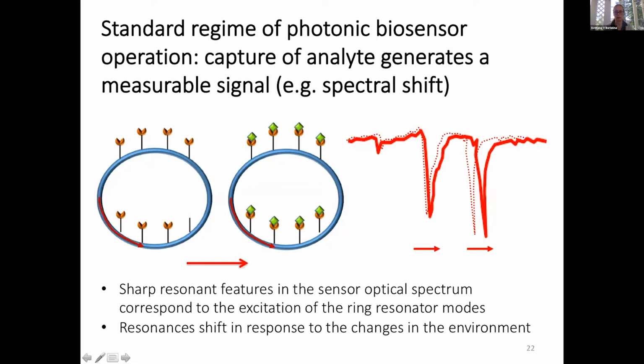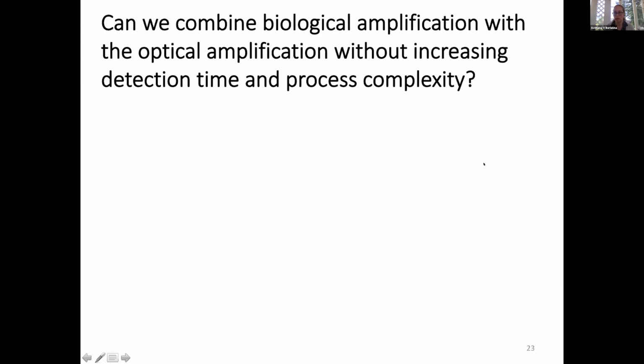So the receptors in this case could be those complementary DNA pairs, the same as used in the PCR test. And then the presence of this captured material shifts the spectrum to usually longer wavelengths. And what you detect is this shift. But if you don't capture enough, if there is not enough of it present in the analyte, the shift will still be very small and it's hard to detect.